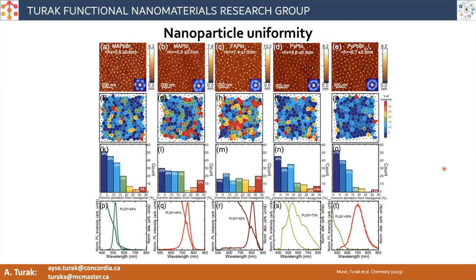And the important thing from our perspective is not only their uniformity, but also their dispersion on the surface. Right? The uniformity of the dispersion, how well we can make that hexagonal close-packed array, can have an impact on the use of these nanoparticles for their collective properties. But this is ultimately one of the biggest benefits of using this approach: achieving a high level of uniformity, regardless of the material that you've picked to make.